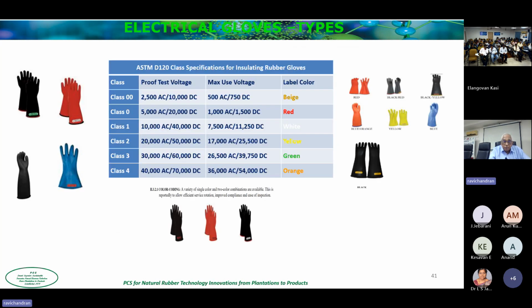These are electrical gloves. We have electrical gloves that can withstand various maximum voltages. You can see the proof. To get a max use voltage of 36,000 AC or 54,000 DC, the proof test voltage it has to pass is 40,000 AC for AC current and 70,000 for DC current. So these all come in various colors. They're made from natural rubber and they're quite thick.